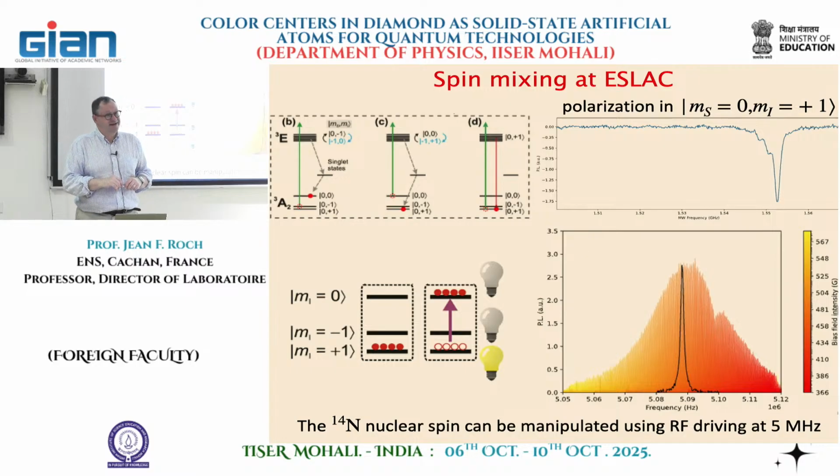And what's very important is that now the nuclear spin coherence can be very long. You will see that. The T2 star, as I mentioned before, is a few hundred microseconds in a very optimized sample. If I take any kind of sample for the nuclear spin, this is much, much longer. It's in the millisecond range. So I can store the information for a longer time in this resource that the nuclear spin provides.